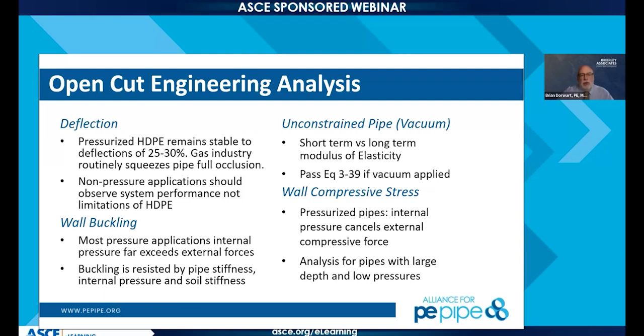The important part of this is if you have bad backfill, you forget to compact it, which sometimes happens, that material is going to start over time loading up on your pipe, and your ovalization will start occurring more in the long term. Is that a big deal or not? No, because eventually it's going to stabilize because it's, again, a granular material. But soil is very important, and that's where the modulus E prime comes in.